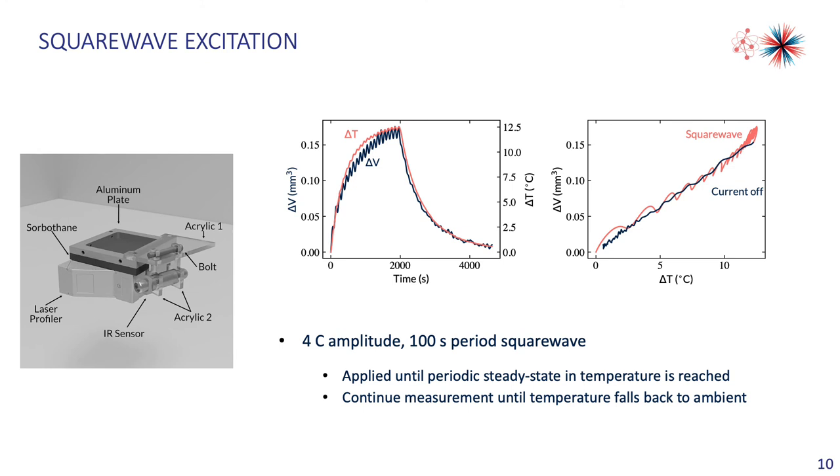As the temperature decreased, the expansion was linearly decreasing, while the small SOC perturbations were just deviating it off of that line.